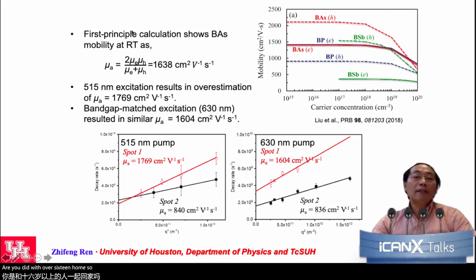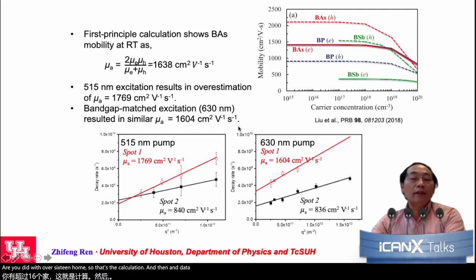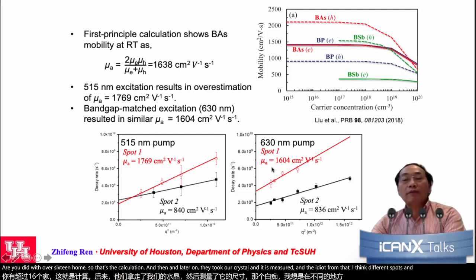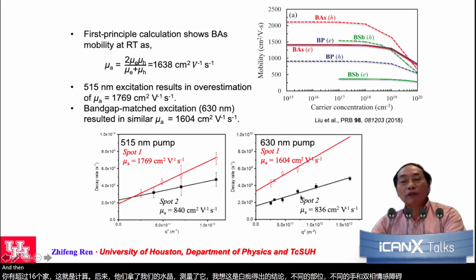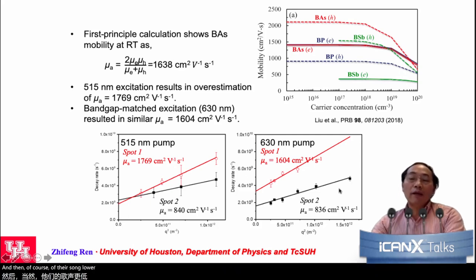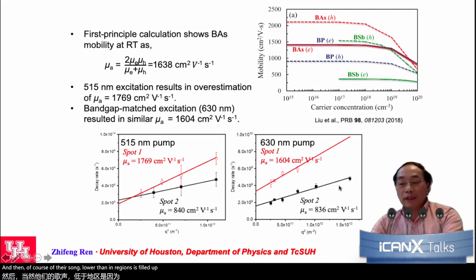So that's the calculation. And later on, they took our crystal and did the measurement. And they did find that in different spots there is bipolar mobility of 1600. And then of course, there are some lower value regions because of the non-uniformity of the sample.